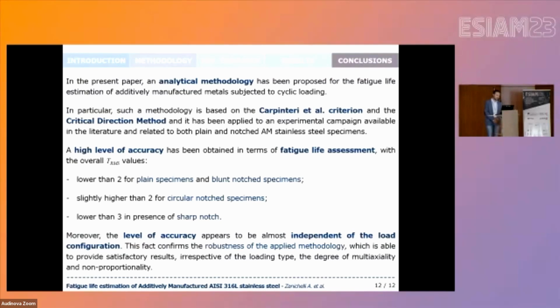Moreover, the level of accuracy appears to be almost independent of the load configurations, and this is a very good point that confirms the robustness of the applied methodology, which is able to provide satisfactory results irrespective of the loading type, the degree of multiaxiality, and the degree of non-proportionality.